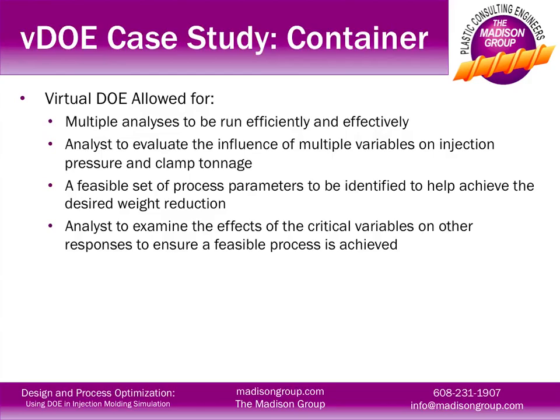In conclusion, virtual DOE allowed for the effective and efficient simulation of numerous analyses. It allowed for the evaluation of multiple variables and their influence on injection pressure and clamp tonnage. It allowed us to identify the minimum feasible part thickness and quantify the size of the molding window. We identified that we could mold the part at the reduced wall thickness as long as we were comfortable molding at a longer fill time and higher melt temperatures. The DOE also allowed us to examine the effects of critical variables on volumetric shrinkage and optimize the process from that point.